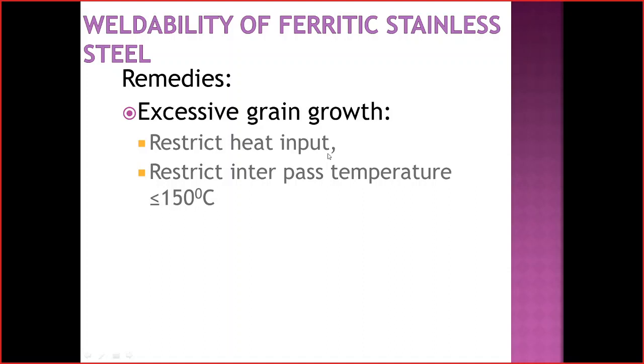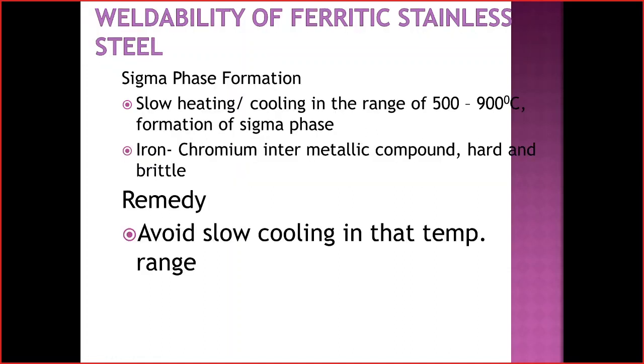Normally when you look at electrodes, a range is given. Suppose, let us say, 70 amperes to 90 amperes. In conventional welding we go for 90 amperes, whereas when you do SS welding, better to go for 70 amperes only. That is the thing you have to keep in mind. And restrict the interpass temperature to less than 150 degrees centigrade. Okay, when you do multiple passes, the number of welding runs also you have to see. Keep to lower temperatures only, not above 150 degrees centigrade.